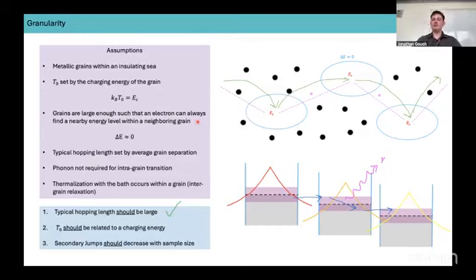So we assume that these grains are very large, so that the average energy separation within the grain is very small. If we decrease the grains, this energy level separation would increase until you get something like a quantum dot. But these are very large, so we don't need to worry about things like this. What this tells us is that there will always be an energy level within a neighboring grain that's nearby. So you don't have to jump very large distances to find a nearby energy level like you do in variable range hopping. This explains why we see this simple activation rather than variable range hopping, because the electron is just hopping between nearby grains.